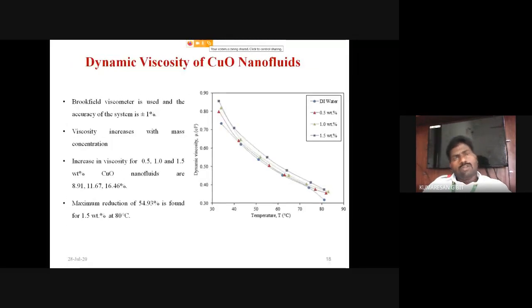The next, dynamic viscosity. Viscosity is one of the important parameters. If you are using a highly viscous fluid for a particular application, it may obstruct the flow and it may deteriorate the thermal performance of the heat transfer process. Here a Brookfield viscometer is used to analyze the viscosity of both nanofluids, copper oxide and aluminum oxide nanofluid, and that is having an accuracy of 1%.